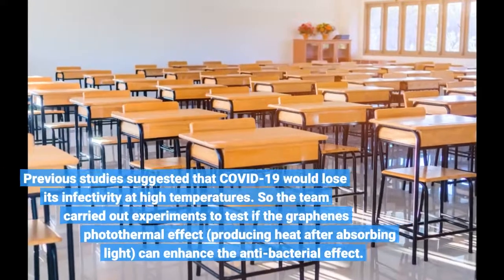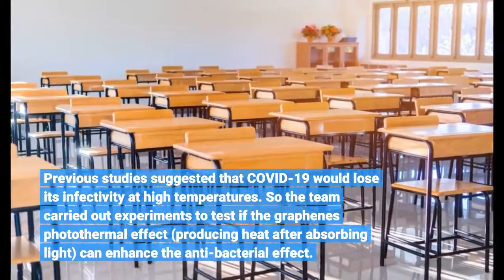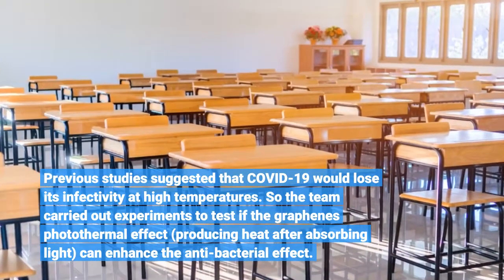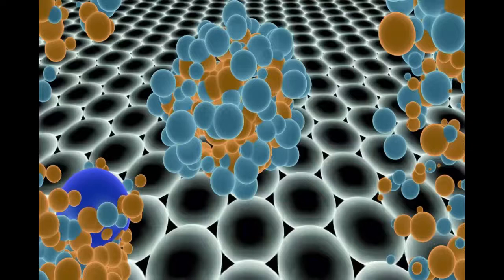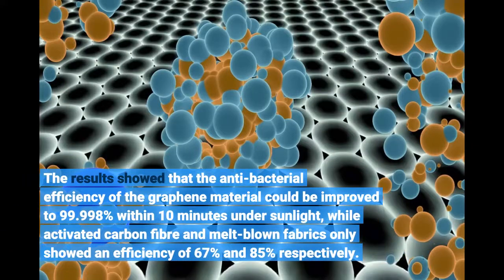Previous studies suggested that COVID-19 would lose its infectivity at high temperatures. So the team carried out experiments to test if the graphene's photothermal effect, producing heat after absorbing light, can enhance the antibacterial effect. The results showed that the antibacterial efficiency of the graphene material could be improved to 99.998% within 10 minutes under sunlight, while activated carbon fiber and melt-blown fabrics only showed an efficiency of 67% and 85% respectively.